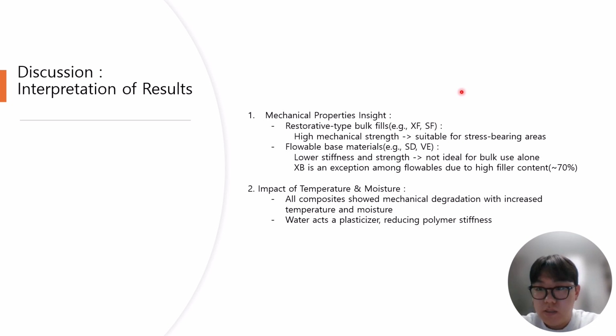Now, let me briefly discuss the main findings and what they mean in a clinical context. First, regarding mechanical properties, restorative-type composites like Extra Fill and Sonic Fill showed high strengths, making them suitable for stress-bearing areas. In contrast, flowable-based materials such as SDR and Venus had lower stiffness and should not be used alone. Extra Base, however, was an exception among the flowables because of its high filler content, about 70%.